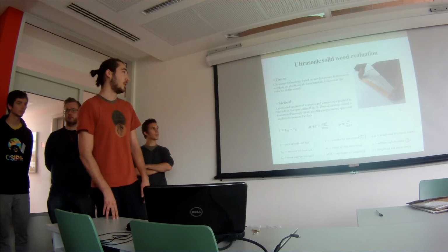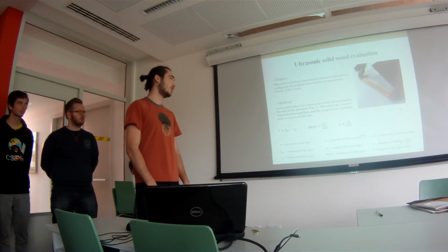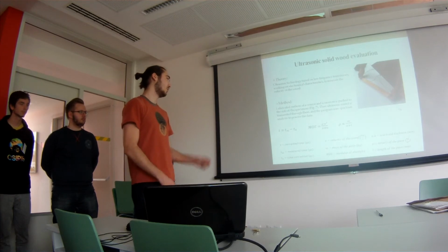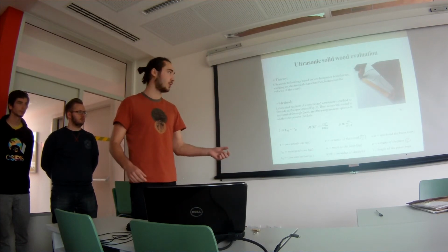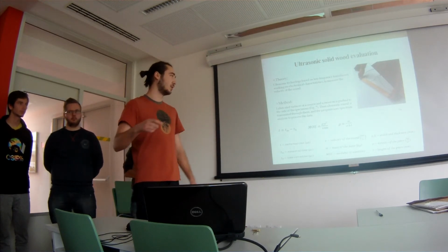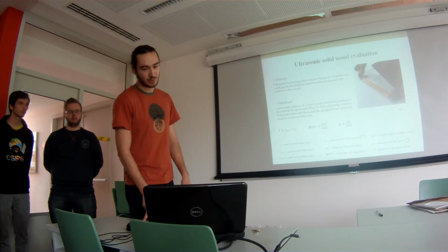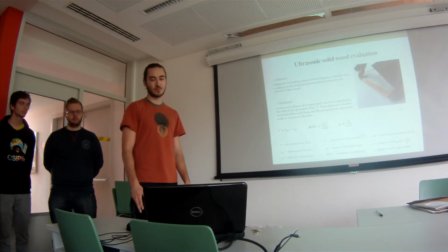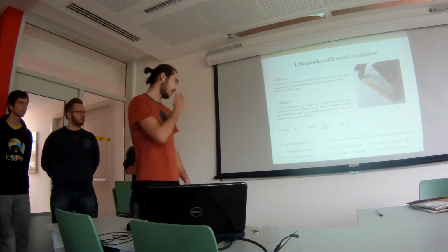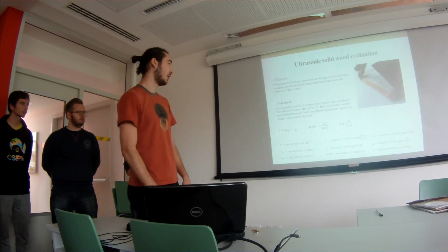Ultrasonic solid wood evaluation. In this case, we used this. On one edge there was a receiver, and on the other a source. So we could measure how fast sound could travel through the wood. We used these equations, so we could calculate them.